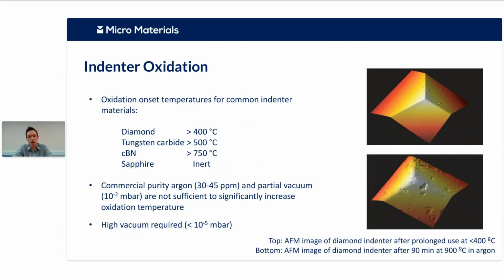On the right here, we can see an AFM image of a diamond indenter after prolonged use at less than 400 degrees C. You can see the pyramidal shape and structure is clearly defined, and that is a nice indenter tip. The image below it is the same indenter after just 90 minutes at 900 degrees in an argon environment. So even with this protective purge, we see the degradation of the tip. Those pyramidal faces are no longer clearly defined, and the tip is severely rounded. This is now no longer usable for nanoindentation. So again, we need to use high vacuum, i.e. less than 10 to the minus 5 millibar, in order to protect the indenters as well as the sample.